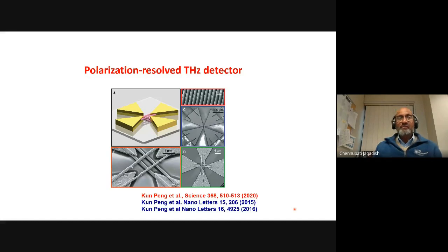And most recently, during her postdoctoral fellowship at Oxford, jointly between us, Oxford University and Strathclyde University, she recently developed this so-called polarization-resolved terahertz detector. In this case, instead of using one or two nanowires, she has nanowires at 90 degrees to each other. You can see the close-up here. These are the bowtie antennas, and here are the nanowires. The challenge has been to avoid contact between the top nanowires and the bottom nanowires. She spent about three years optimizing this, otherwise they'd be shorting. And then she used these to measure the performance of these particular detectors.